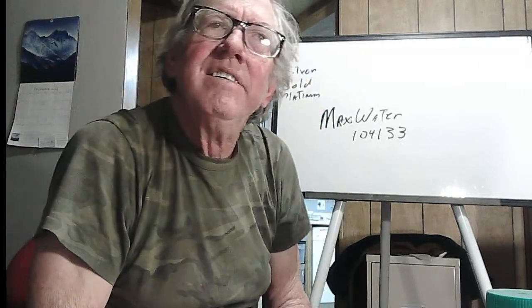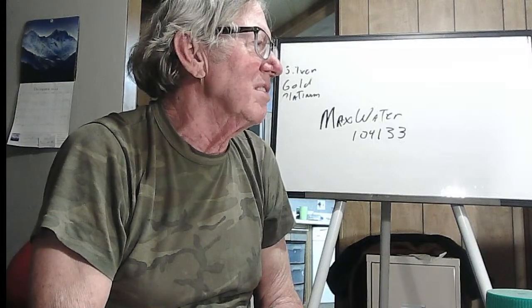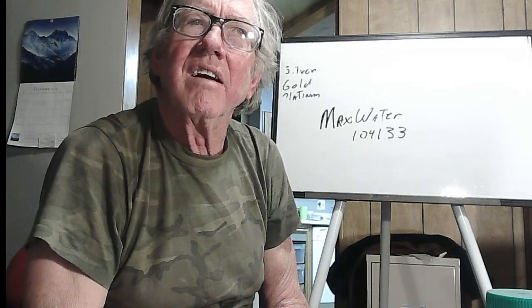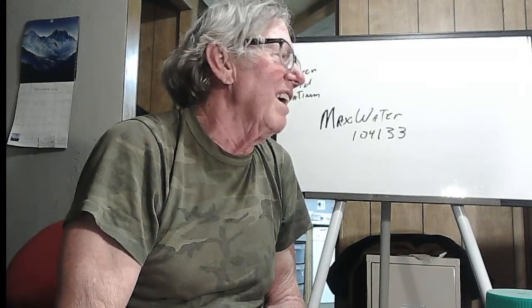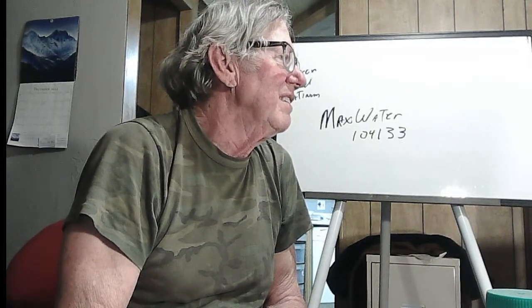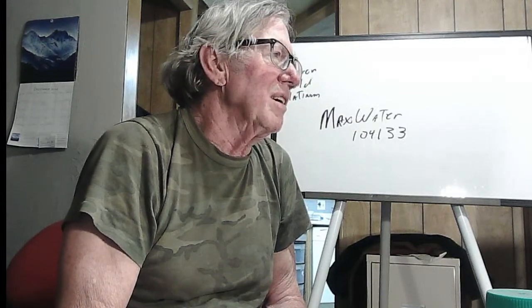What's the Max Water cost? Last we did it, I think it was about $13 a pound, and that was a delivered price. The gold loading, we've been achieving about 3% is all. Theoretically, you should be able to get up to about 10, but we get other stuff loading in addition, and that's one factor. And the second factor is so far we haven't had a really high-grade ore to test it on. Everything's been fairly marginal.